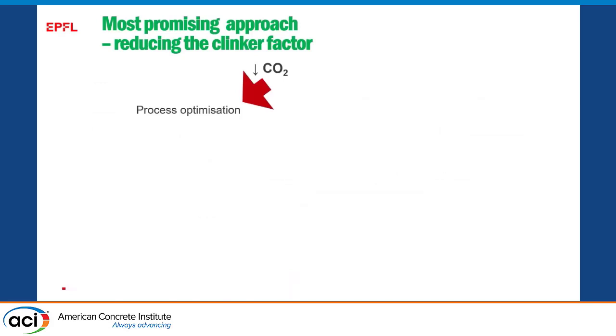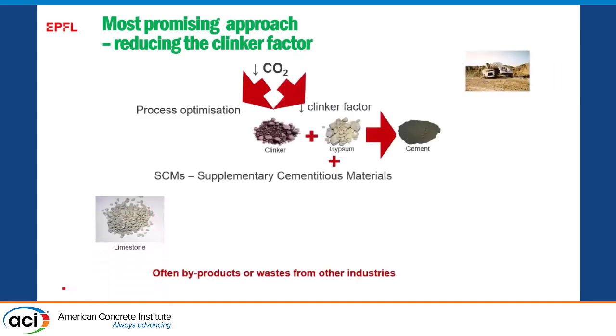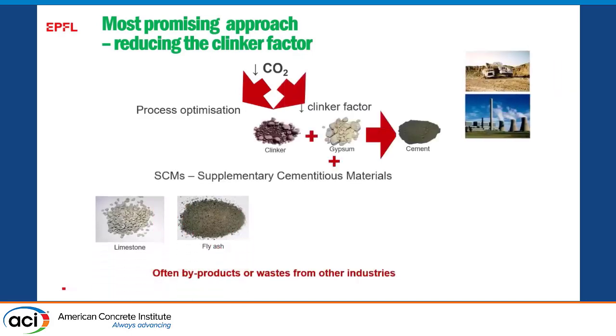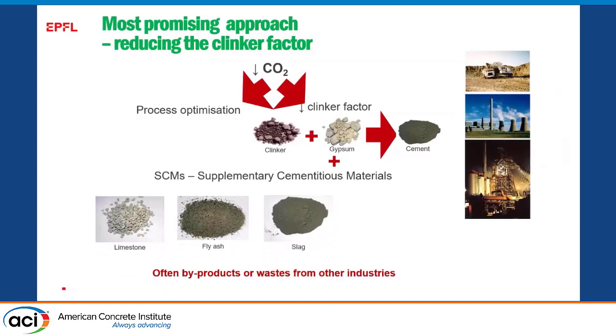So all of this is kind of an introduction to say, this is the analysis. There's no great miracle out there, but there's still a lot we can do with the very simple technology of blended cements or using SCMs in concrete, which we've known for many decades now. We can introduce limestone. This was done 30 years ago in Europe, and it's just being done in North America. I think you've got to move faster to catch up. We've got to see more ambition here to really bring about CO2 reductions. And then we have fly ash, but this is horrible stuff that comes from burning coal, which is the number one thing we've got to stop. And slag, which is a very nice SCM, but unfortunately comes from this very CO2 intensive process of producing steel.